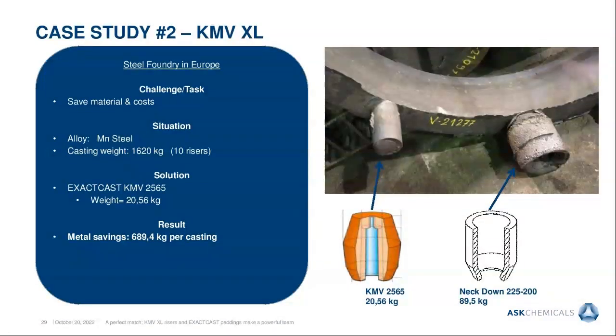In this second case study, we are also talking about a steel foundry in Europe. In this case, the casting was a manganese steel one with a total weight of 1620 kilograms, and the layout consisted of 10 riser positions. In the first trial, we wanted to change only one of the positions, from the traditional solution consisting of a neck down with 90 kilograms to the KMV 2565 with a total weight of 20 kilograms. In the end, the results were great.